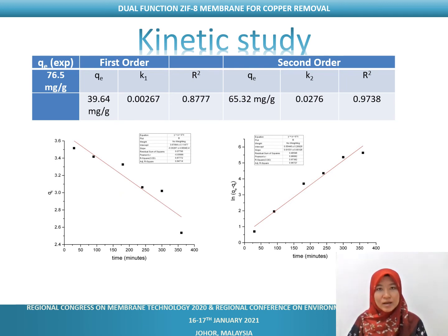The kinetic data of pseudo-first order and pseudo-second order is shown in the table. The results indicate that the adsorption kinetics of the ZIF-8 membrane fit the pseudo-second order model better than the pseudo-first order model, with a correlation coefficient value of 0.9738. Hence, it can be established that the adsorption of copper-2 on the ZIF-8 membrane follows the pseudo-second order kinetic model. Additionally, the theoretical qe value from the pseudo-second order model was close to the experimental value.